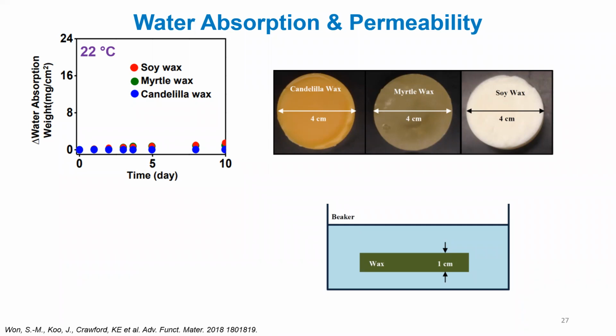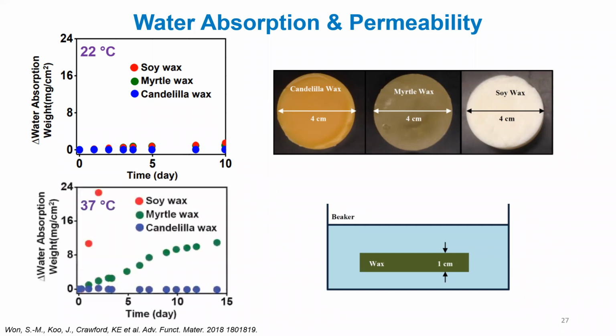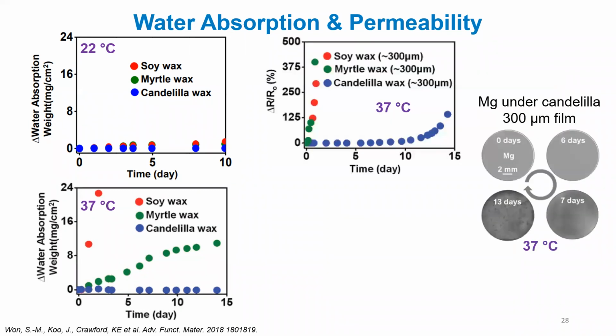So we thought, well, eventually we'd want to use this maybe for an implantable electronic. So let's increase the temperature to body temperature, 37. And then finally, we actually started to see some difference. The soy wax absorbs a significant amount of water at body temperature. The myrtle absorbs some water, but the candelilla still stays pretty low. And so that might be our winning candidate to pursue. So we looked at two other things then for the candelilla wax, and we included the soy here too, just so you can see that.